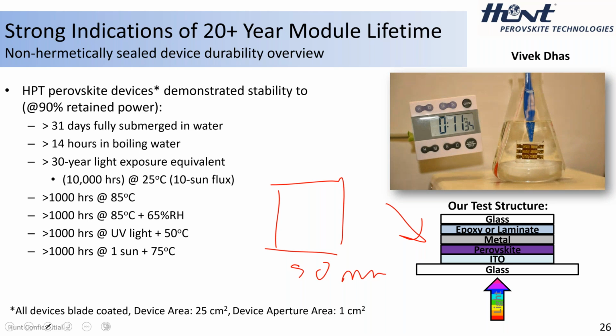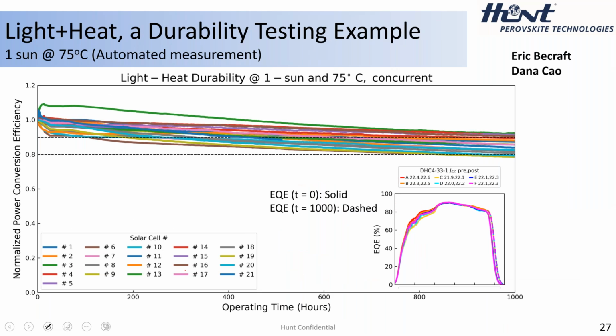And I will tell you, I think I've evidenced this very strongly in the previous slides. Every time I showed degradation, there was light involved. So light is a strong driver of the degradation. And so this last test was one of the harder ones for us to pass. It took special chemistry to stabilize the material fundamentally to be able to pass this test. So it's not something you can package out. I can package out humidity, I can package out oxygen, whatever else, but I cannot package out light or heat. So an example of this durability data. So you can see over the course of 1,000 hours, concurrent one sun and 75C.